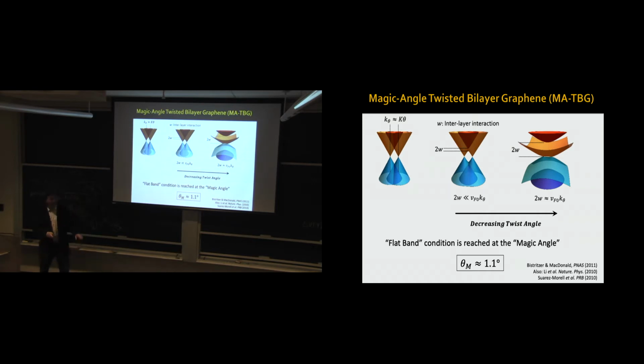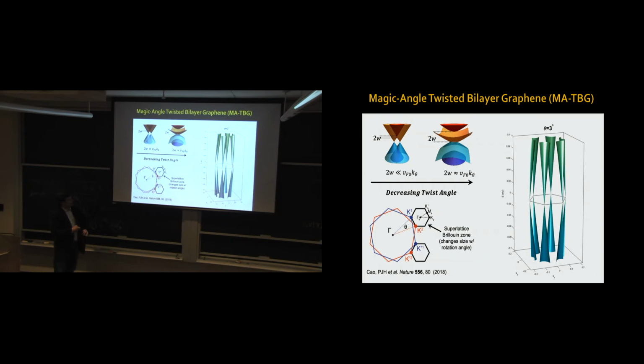This is a schematic cartoon of what happens. Let me show you, in a calculation, what actually happens. Remember, we have the two graphene sheets with two reciprocal spaces. If I join the corners of these reciprocal spaces for the two graphene sheets and complete this hexagon, this is my superlattice Brillouin zone, because I have a real space long moiré wavelength. In reciprocal space, my superlattice Brillouin zone is smaller - long in real space means short in momentum space.